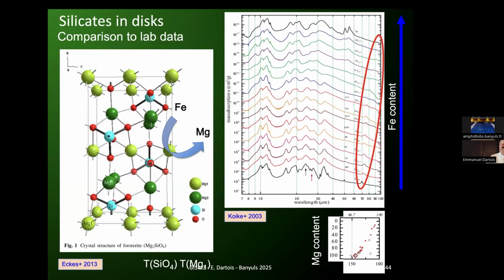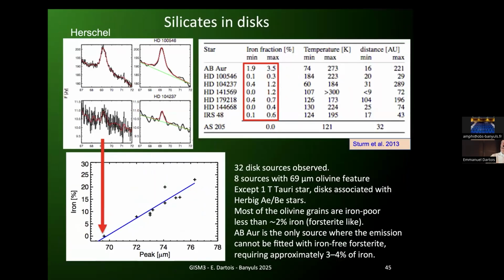And here you have the magnesium content as a function of the position. That is what's compared to spectra. And basically, the iron fraction was almost always compatible with no iron at all in these silicates, except for AB Aurigae, where it was 3%, 4%. So basically, you end up in these situations with grains that are iron poor, and you need a low fraction of iron in these silicates.